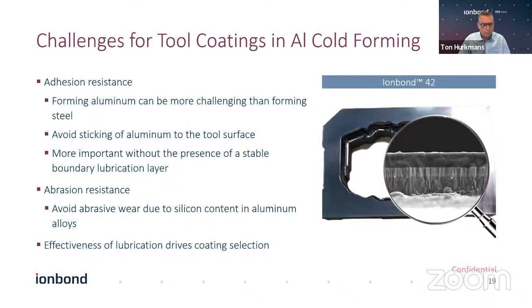The abrasion resistance is also key. The aluminum is not just aluminum, it typically contains silicon particles as well to get the strength into the aluminum sheet materials. And that will also contribute to excessive wear on the die. But this hard coating with a DLC, diamond-like carbon top coating, is also resistant against abrasion.